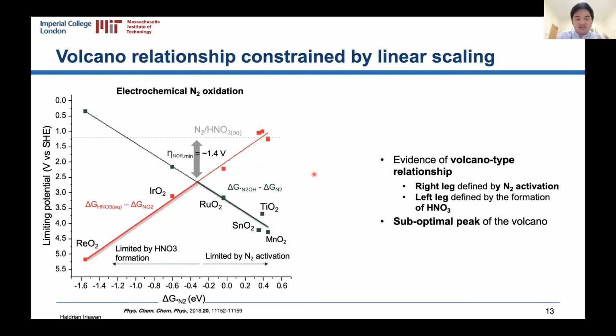We can actually understand the limitation in a slightly different way. Here I plotted the limiting potential, which is essentially the potential that we need to overcome the reaction steps. And as we go down, it becomes more oxidizing. And here we actually see a sort of volcano trend. On the right side of this volcano, for these materials, the reaction steps are limited by reaction activation, where the first step is most challenging.